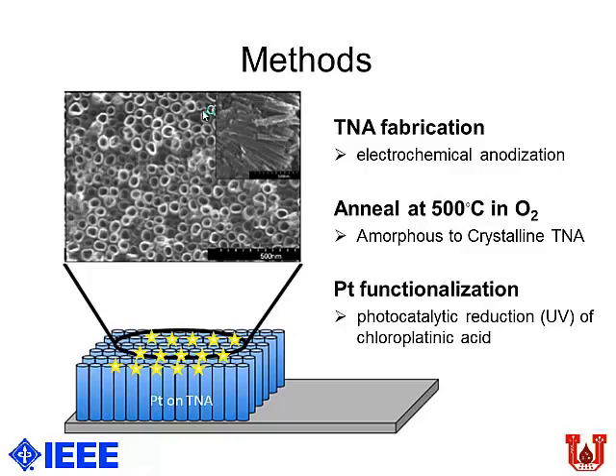What you do is you dip the whole system in a chloroplatinic acid, which is an acid of platinum, and then you shine UV light on it. So your platinum would just get deposited on your tubes. You can control the amount of platinum that's deposited by the amount of time for which you apply UV light, also the intensity of the UV light. So it's a pretty simple method of making the sensor.